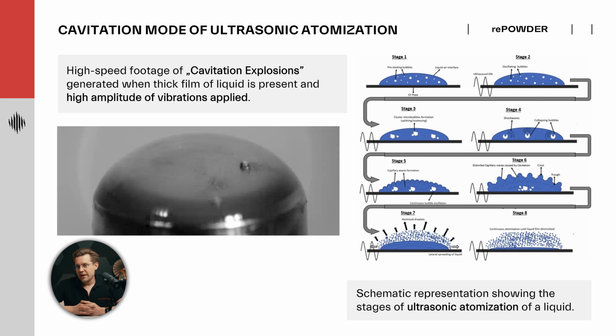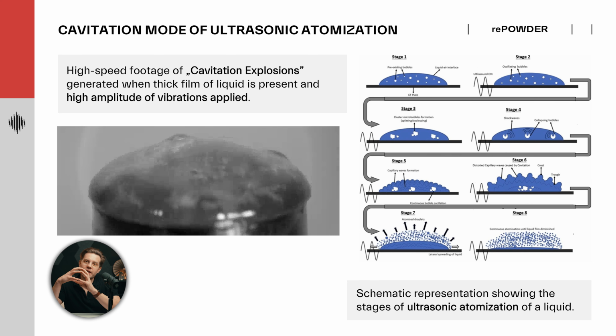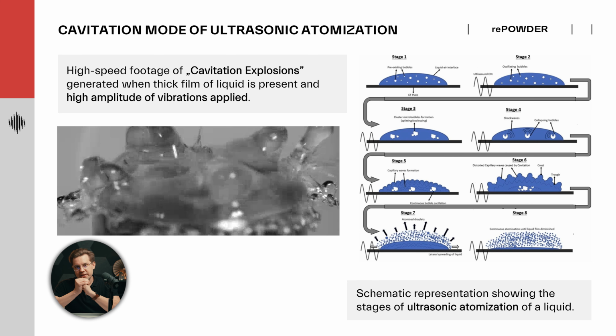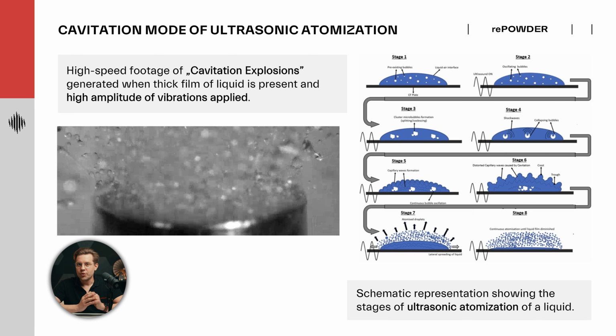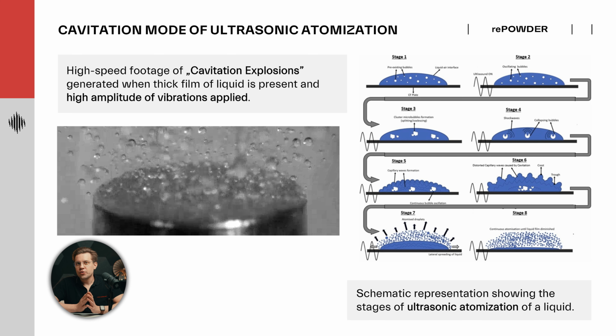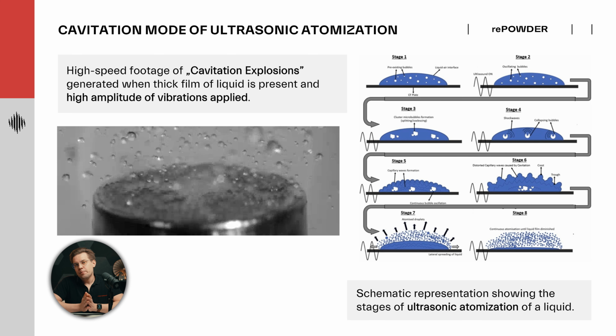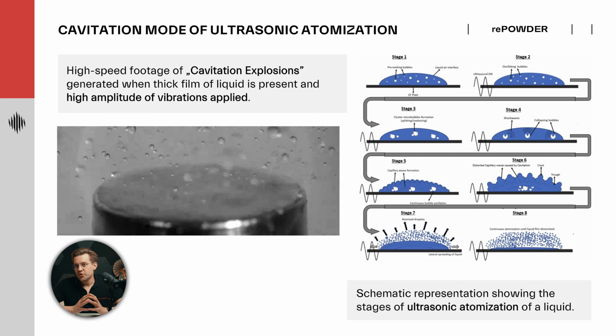If we increase the amplitude, there is an additional effect present: cavitation. Cavitation is a phenomenon where a void is formed in the liquid melt, and when it collapses, it creates a shockwave, a micro explosion that ejects both tiny and large particles, and it basically broadens our particle size distribution. So the larger the amplitude, the broader the particle size distribution, due to those micro explosions from cavitation.